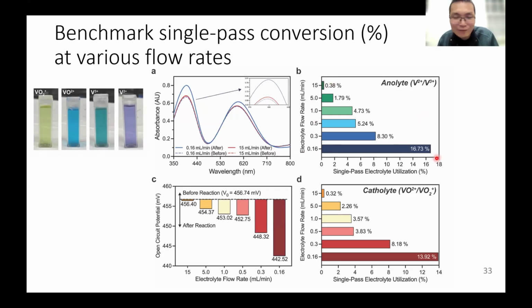And then that's actually the first time this number is measured in the literature, because people usually don't care about this single pass conversion. And then this is using vanadium chemistry. So vanadium has different colors, so we're able to use the change of color to measure how much vanadium reacted.